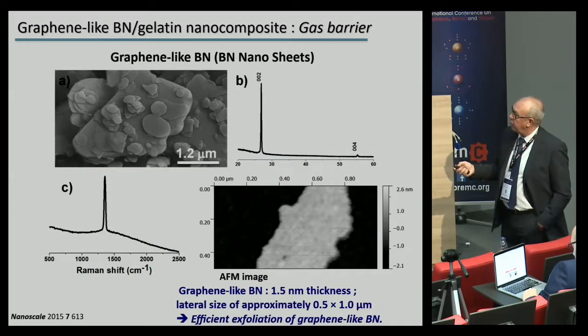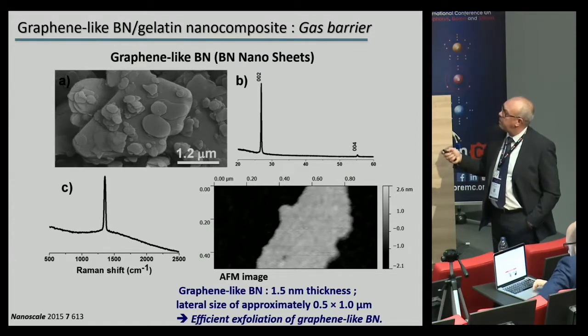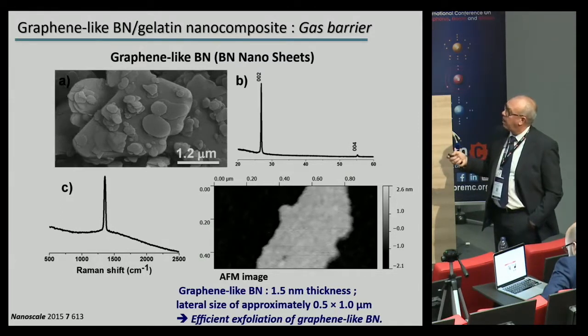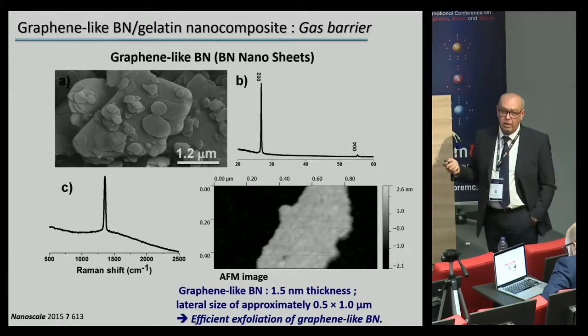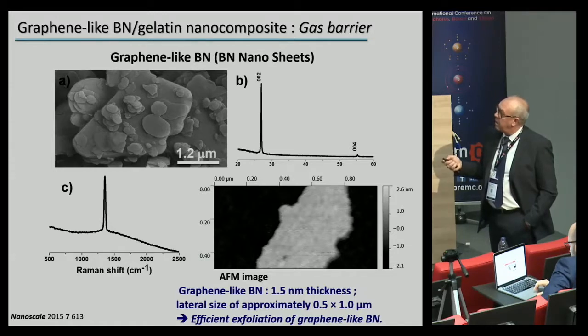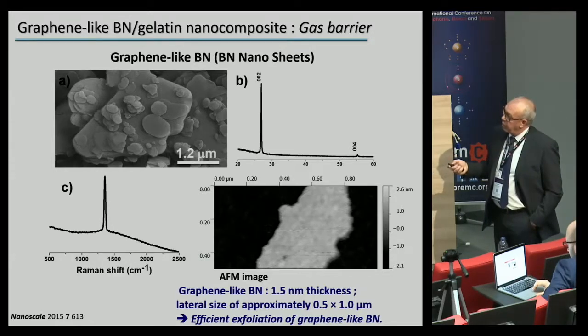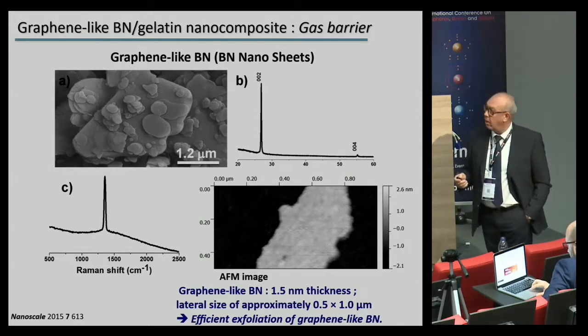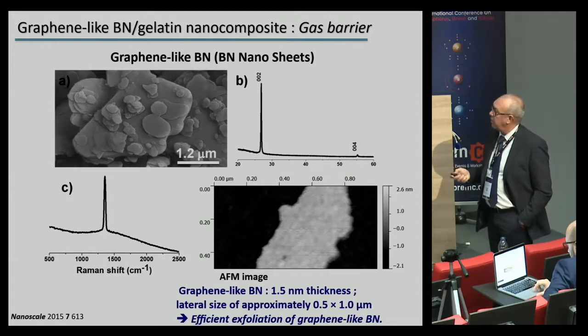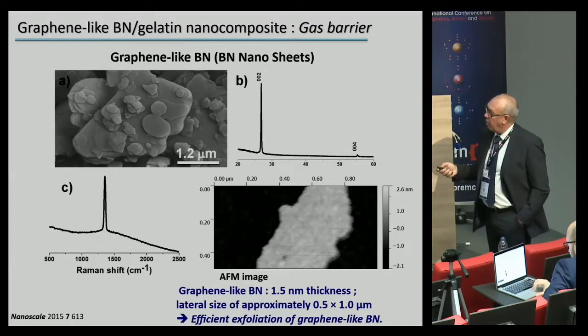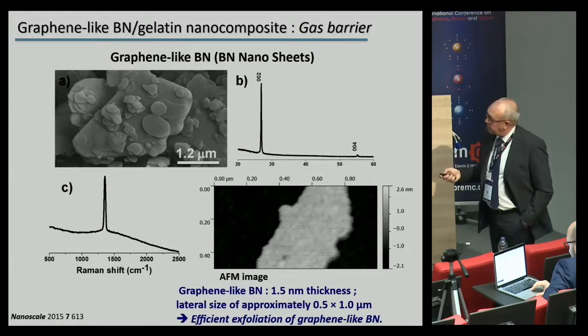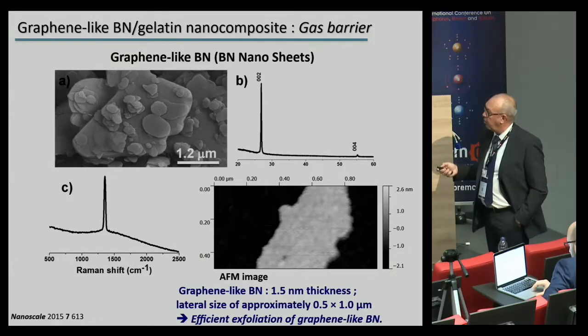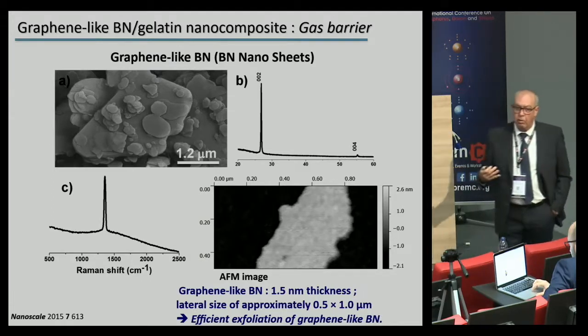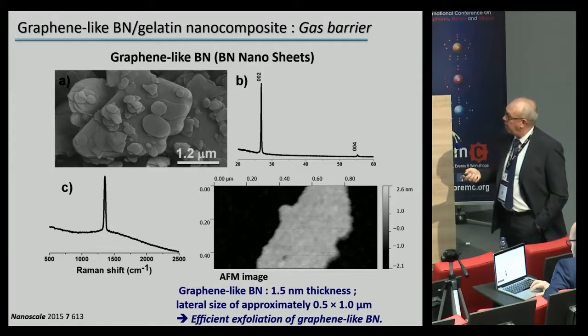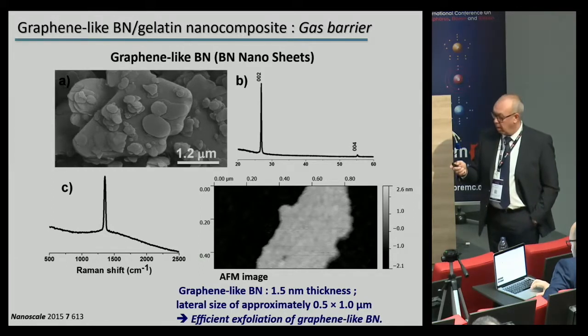So this is a characterization of the nanosheets. You can see here the X-ray diffraction data showing the very good crystallinity of the boron nitride particles we have used. This is the SEM picture. Here the Raman spectra, which is perfectly in line with the data of BN, and with this AFM image, we can deduce that BN displays 1.5 nanometers in thickness, with a lateral size of approximately 0.5 to 1 micron, showing the very efficient exfoliation of these boron nitride nanosheets with this very simple method.